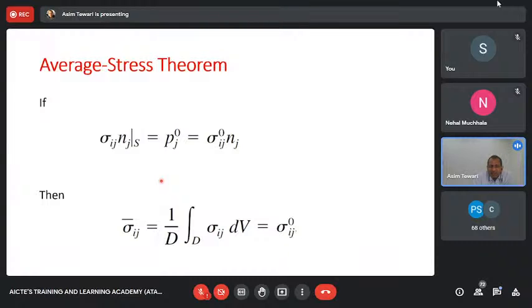Another very simple thing which you need to understand is the average stress in a volume, in this case the entire sample, if you have a traction boundary condition. So this is the boundary condition. If I say that there is a force being applied on my system from outside, given by sigma ij nj, which means that this is a force in the i direction, then I will end up having a body which will have an average stress given by this stress tensor. Sigma ij nj is the force which I'm applying in the i direction.